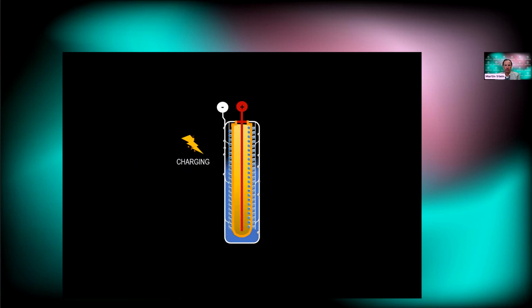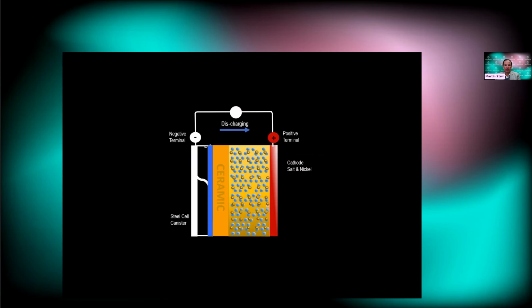When we charge the battery, the sodium ions go through the electrolyte, and when we discharge the battery, the sodium ions migrate back through the electrolyte. They cling back onto the chloride ions again and become salt or sodium chloride, and the charging and the discharging of the battery continues along that path, all within that stainless steel cell that we saw earlier.